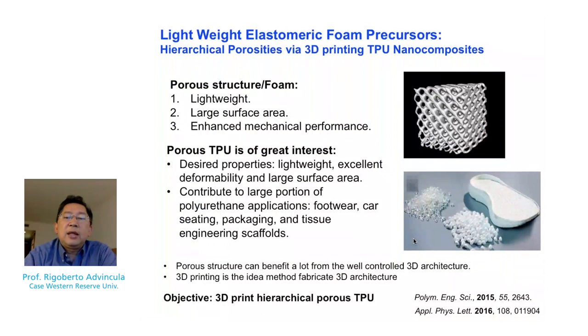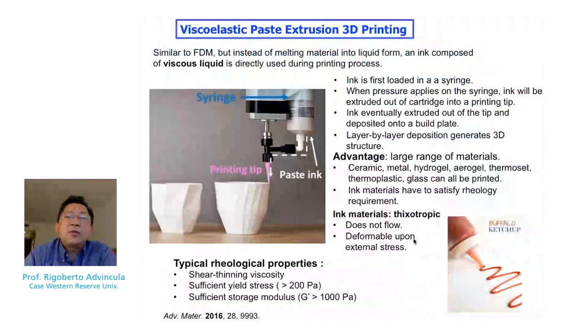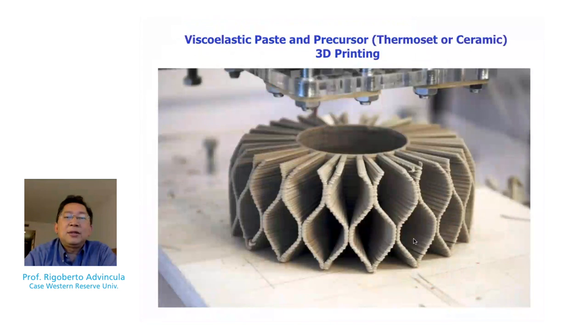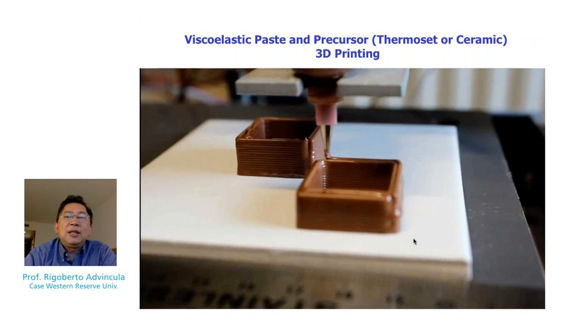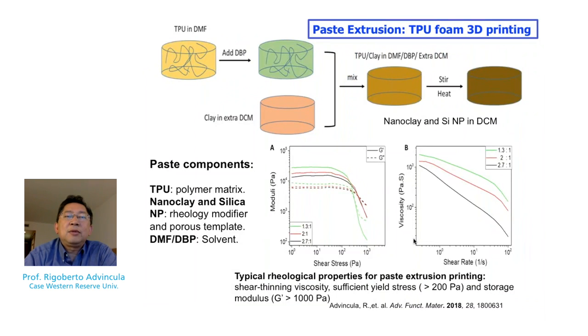So what we have done, and this was a paper that was published last year, is we use TPU, a plastic, as a precursor for making foams. So foam here was generated by making porogens based on the nanoclay incorporated. And we use viscous solution printing to prepare this material. So we printed a viscous base with the right shear thinning viscosity, yield stress. I'm showing here that we can 3D print ketchup like this. We can 3D print cement like this, or we can 3D print chocolate like this. But in this case, we made a 3D printable thermoplastic polyurethane. And I'll show you the electronic application of this.